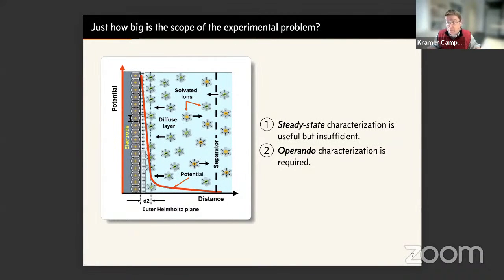Assuming we can find an appropriate operando experimental tool, why not just look at the surface under steady state reactive conditions? Of course, this is an interesting and important experiment to do. But our view of the problem is that this is inherently insufficient, right? The difficulty here, of course, is that you do not know from the experiment whether the species that you observe at the interface, say, under steady state reactive conditions, is an intermediate in the chemistry you care about, or whether it's some kind of unwanted side product. You don't know how the changes that you observe are related to the chemical reaction that you care about.